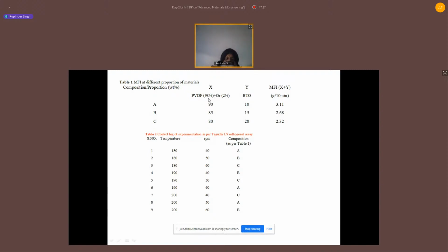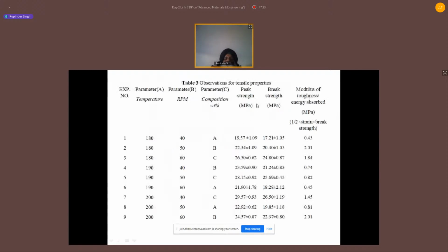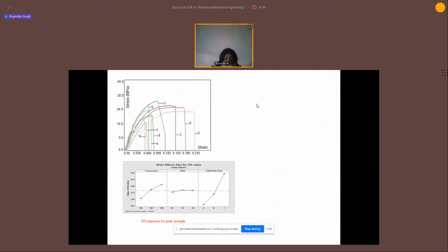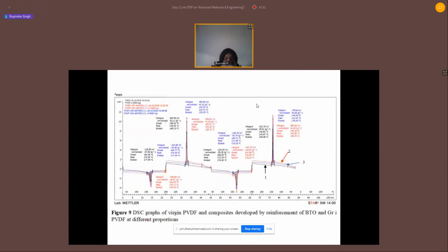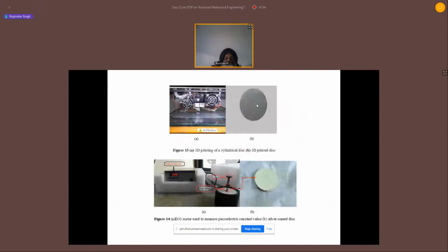So with this proportion, different BTO, barium titanate, was reinforced, and we tried to prepare the disc. Then we tried to see their peak strength, break strength, their modulus of toughness, their stress-strain curve, their thermal stability, and their d33. We were able to get 20 picocoulomb per Newton as a piezoelectric effect, right?